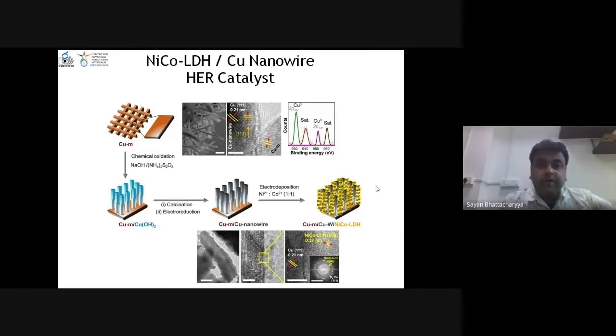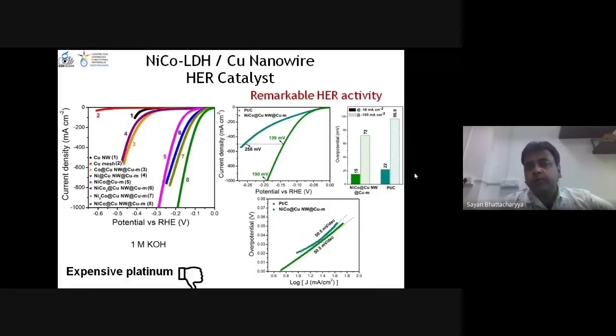And the self-supported catalyst, this is a simple one, but I'll tell you one very, very interesting thing here, that you start from a copper mesh. Copper mesh, anybody or any one of us can get from the market. So copper mesh, you chemically oxidize it, you create copper hydroxide rods on the top, you do electroreduction, you get metallic copper nanowires. Now you deposit a catalyst, which is a layered double hydroxide on top of it, and they wrap around all these rods. Okay, this is the rod. You see the catalyst is wrapping around it. The beautiful thing I show you now.